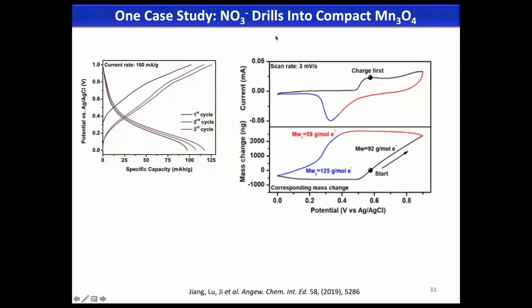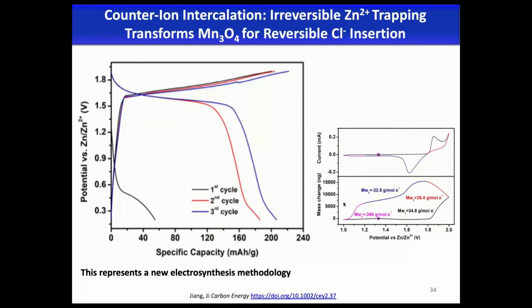Now, this is another example, Mn3O4. It's a crystal, a pretty solid, I would say compact structure, and we can have ammonium and nitrate ions inserted. We have EQCM, electrochemical quartz crystal microbalance, evidence to show that we have nitrate in. All right, so this is another example. Again, we have chloride inserted into Mn3O4. So far the evidence shows that if you have some zinc ions trapped in the first reduction, that's going to help the following oxidation of the structure, simultaneously having chloride ions inserted.